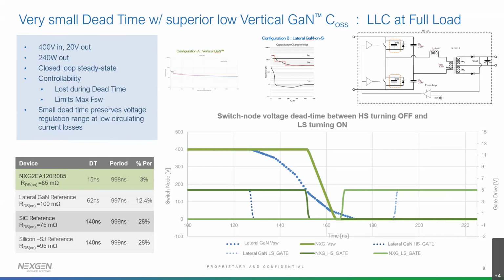Whereas the lateral GaN device, which we have used as a reference, state of the art, and I would say best in class, actually needs 62 nanoseconds of dead time. And if you go to silicon devices, the dead time becomes even higher. So even in a situation where we have zero voltage switching and the output capacitance really is not this important, the high output capacitance of traditional devices creates a large dead time, and that has two effects.